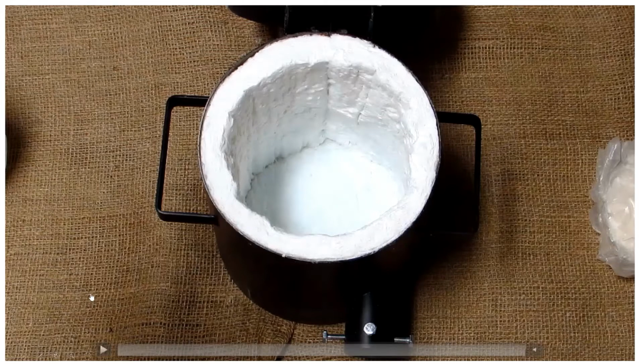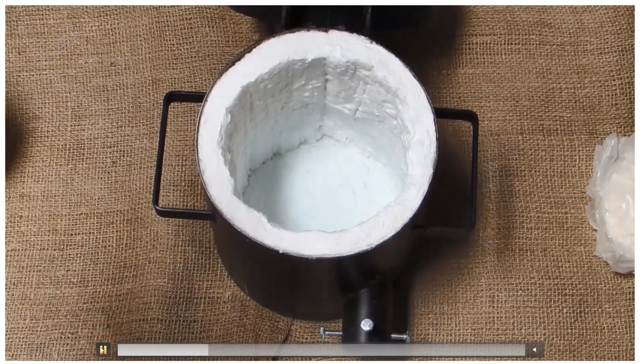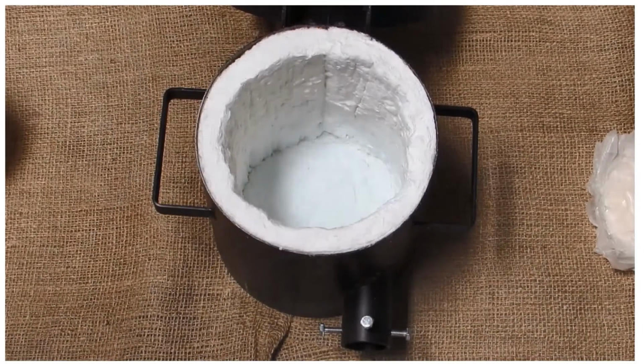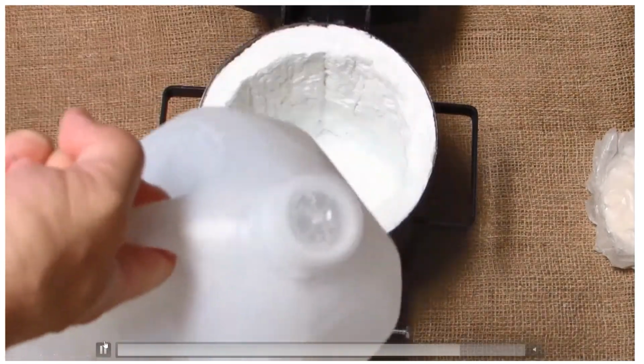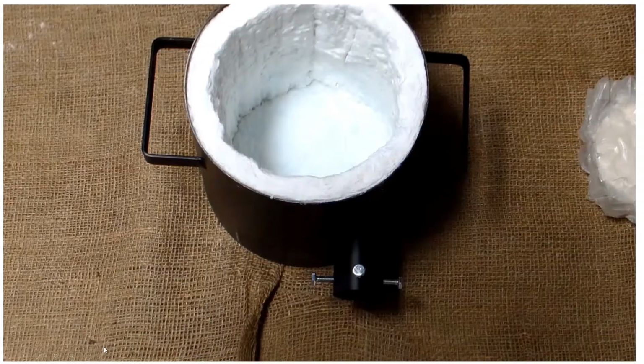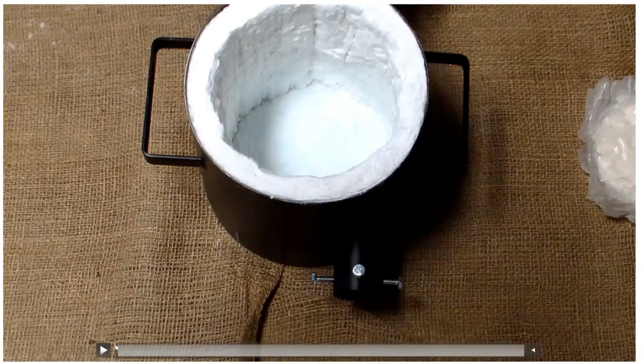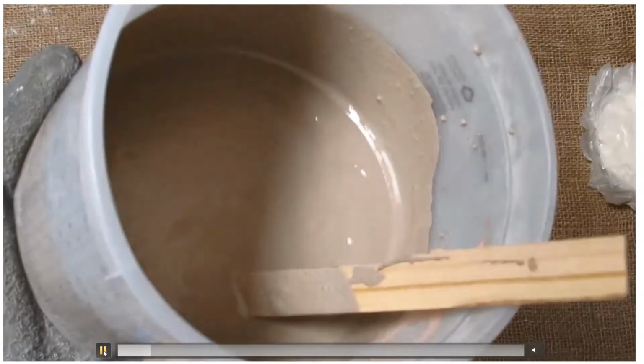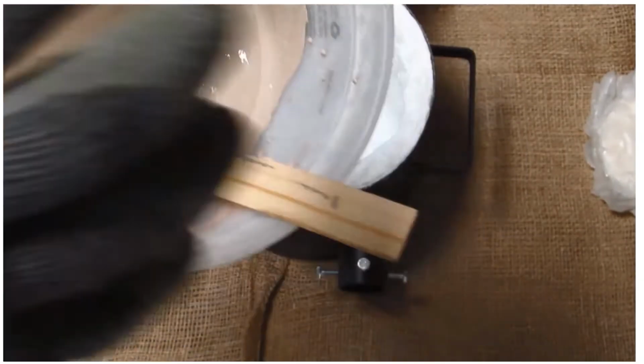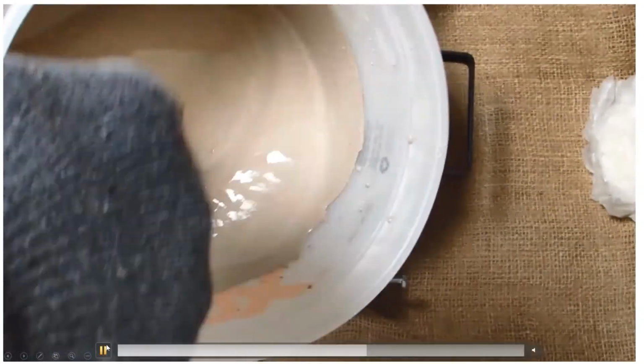I went ahead and coated the furnace with the mortar that came with the unit simply because I had it. I could have run the furnace a little bit more safely after it was rigidized. The whole idea of coating your ceramic wool is so you don't aerate the fine particles and have that become a breathing hazard. And so I took the mortar that came with the unit and combined it with DI water. There were no ratio instructions. It said to mix the mortar until you had the consistency of ranch dressing, and to me, this was the consistency of ranch dressing.